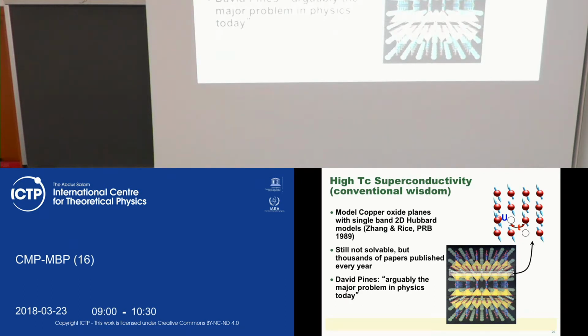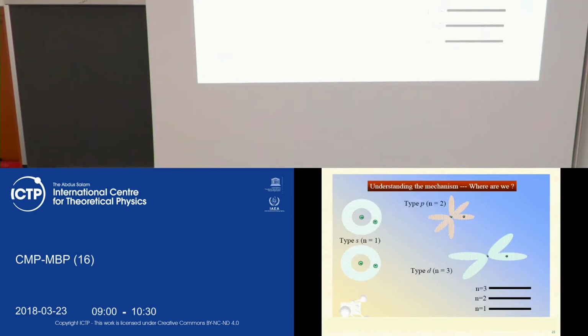So people started to consider the Hubbard model. However, the perfect Hubbard model at half filling, as I said, is an antiferromagnetic insulator. One needs to add certain holes which superconduct. As I said, the superconductivity appears because you dope the system with oxygen, which produces extra holes, but the sign of the carriers is not so important. One of the first attempts to explain superconductivity was to consider the two-dimensional Hubbard model slightly away from half filling. But then it was very quickly understood that since the background is antiferromagnetic and you introduce holes inside of an antiferromagnet, which will then proliferate along your antiferromagnetic background,